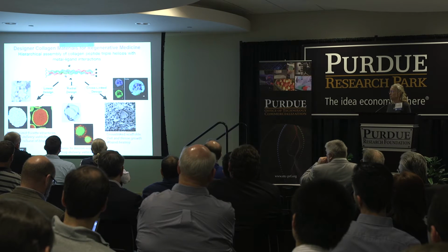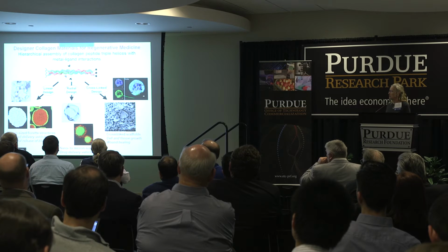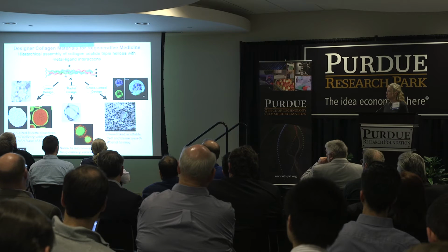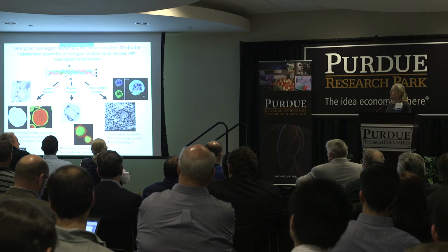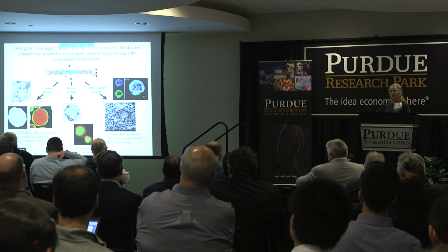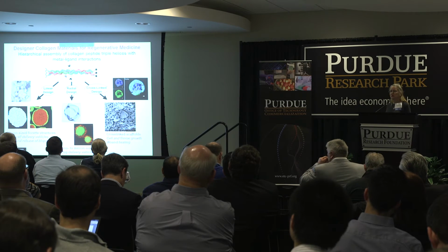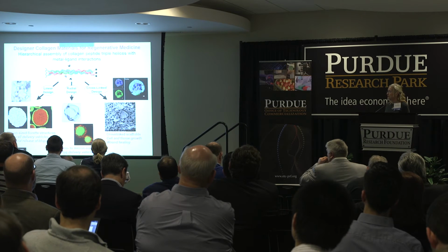Here you're looking at a three-dimensional matrix that is highly cross-linked and has pores that are available for cells to be able to be encapsulated and grow. In addition, we can also start to grow tissue within these materials. And we've been looking at this for cell and tissue growth and also for wound healing applications. So a single peptide, by the way in which you decorate it, can allow you access to all this multitude of different structures. And since they're held together by metal-ligand interactions, one can use a light treatment of chelators for the metals and also release any of the encapsulated materials, cells, or tissue that are entrapped within these materials.